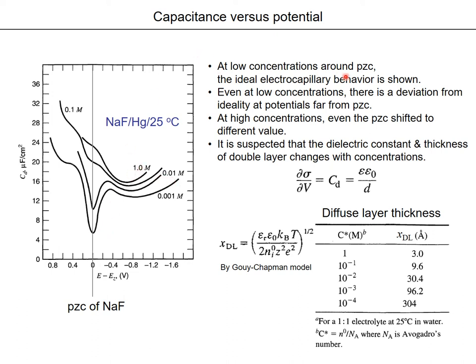At low concentration around the point of zero charge, for example, 0.001 and 0.01 molar around here, the ideal electrocapillary behavior is shown. So at the point of zero charge, the minimum value of capacitance is obtained. However, when you go far from the point of zero charge, the capacitance goes up in the negative direction and also in the positive direction. However, even at low concentration, there is a deviation from ideality at potentials far from the point of zero charge, like that, here and there.